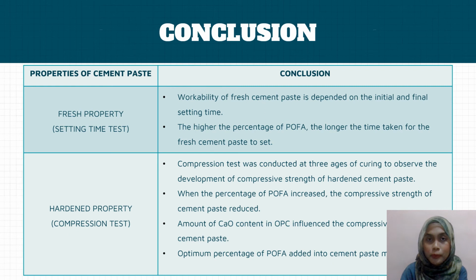The second objective of this project is to determine the hardening property of cement paste by conducting the compression test. The compression test was conducted at 3 different ages of curing, mainly to observe the development of compressive strength of the hardened cement paste. Also, it is found that the compressive strength will be reduced as the percentage of POFA increases. This is because when the percentage of POFA is high, the amount of CaO content in OPC will be low, and it slows down the process of hydration, therefore it reduces the compressive strength of the cement paste. Lastly, to conclude, the optimum percentage of POFA added into the cement paste mixture is only 5%.